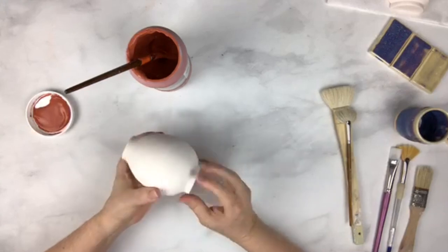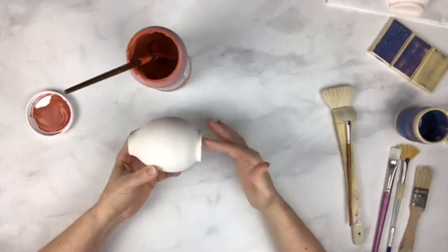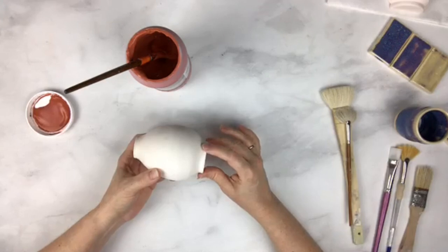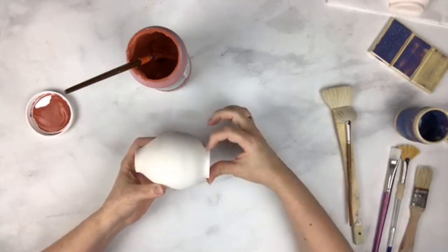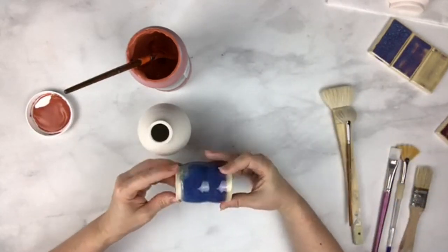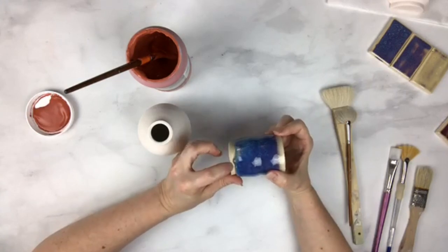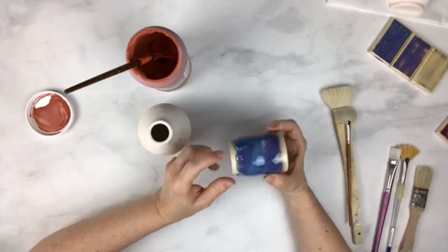I have my vase here. I've already applied glaze on the inside — just a clear glaze. I'd like to point out the foot. One of the things I do to keep glazes from running too much is to trim a sharp angle in the foot. It helps to slow down the glaze. For example, this cup has three coats of Flambe applied with a sharp angled foot, and the glaze kind of stops when it gets there and does not run all the way down. A little bit of space plus the angle is what slows it down.